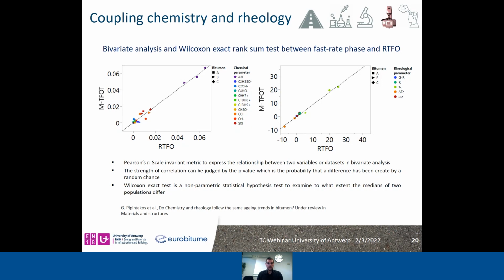And both show that the values that are captured have a good correlation between the chemical parameters of the two different aging states, and also the chemical and rheological parameters of them showed a good correlation between the states. Then each parameter was also scrutinized in terms of differences for the medians, and this was done with the Wilcoxon exact signed-rank test, which is a non-parametric statistical hypothesis test that shows what we were searching for, if the differences for one parameter only are considerable. Also, the Wilcoxon test supported that between the two states we have a good agreement for both the rheological and chemical parameters, which in other words means that rheology and chemistry, independent of the aging protocol that is used, if one coincides, for example, rheology, then chemistry to some extent follows the same trends.